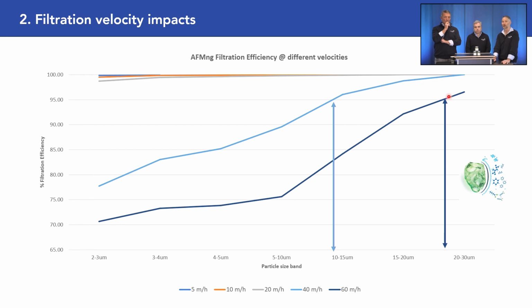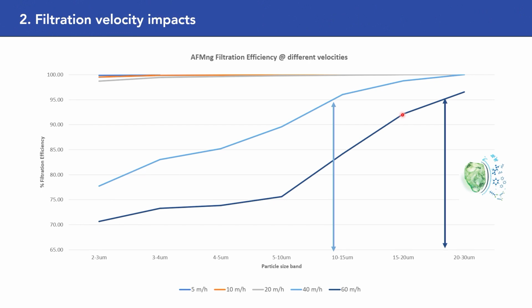Your particle removal efficiency rates. So the reason why we always make a recommendation on filtration velocities is because of this kind of data that we see. And this, ladies and gentlemen, is now with AFM-NG. If you would compare these with a very good quartz sand at 20 meters, the gray line would look like the dark blue line that you show here. So it's a huge difference, right? What that means is that with AFM-NG, you can double the filtration velocity and still have the same filtration performance.